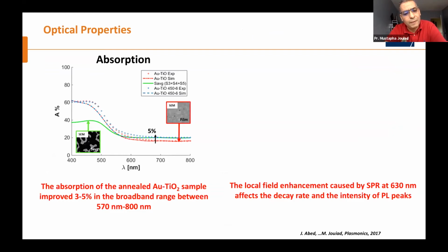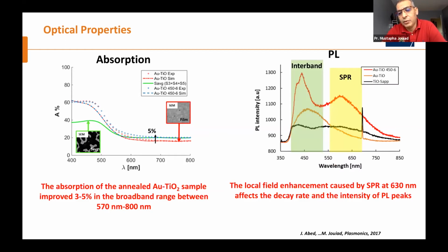To check the absorption, I can show you here the evolution of absorption based on the annealing. You can see the gray and the red lines, which are the film without any annealing, and the green and the blue with annealing; you have a 5% increase in absorption in the visible region. This is only for the film. We also did some PL, photoluminescence, for titania and for the annealed composite. For the annealed one, the red curve, we have very sharp absorption in UV, which is normal because we have titania, but we created an SPR phenomenon in the visible region. This is the origin of the enhancement of absorption in the visible region.